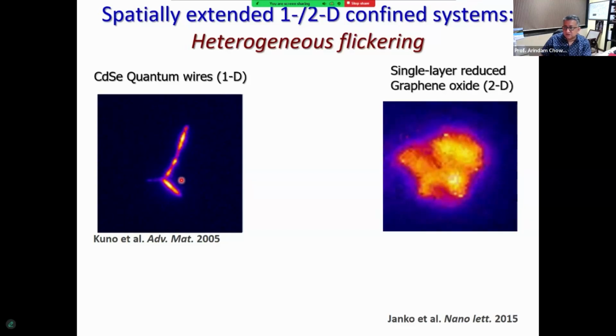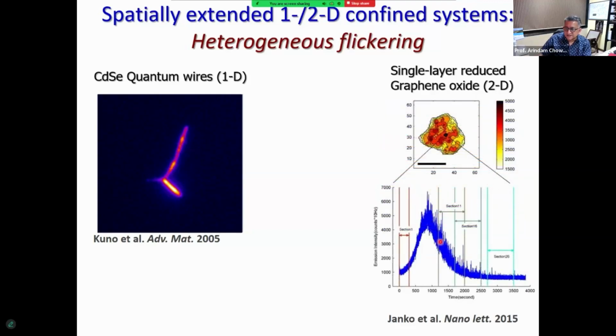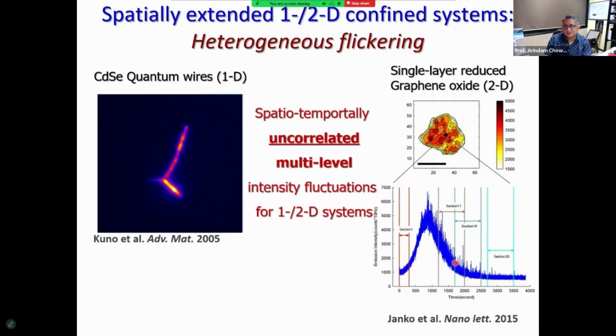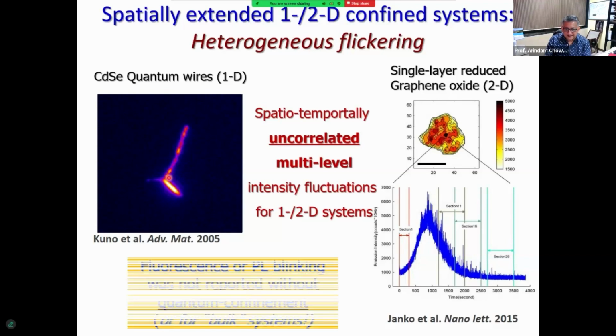The same group also looked at a 2D system, single layer reduced graphene oxide, where you start seeing these small fluctuations. And if I plot the intensity, you will start seeing the spikes. These spikes are essentially not uniform over space. They are uncorrelated as a function of space. The events that happen at different points of time at different locations are not correlated. And they're multi-level fluctuations, which I would rather call flickering rather than blinking, right?